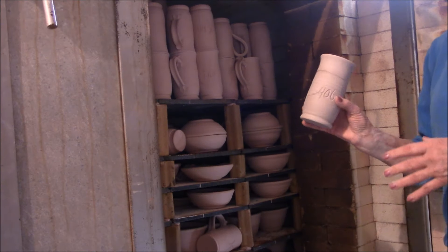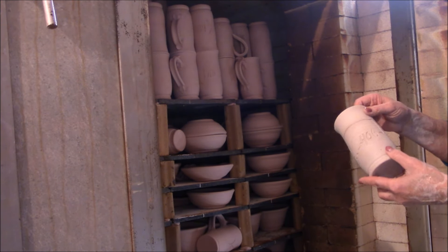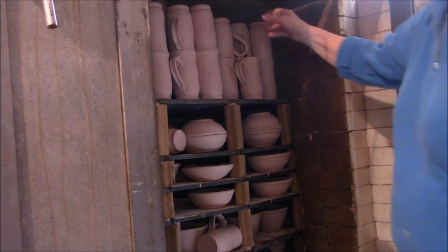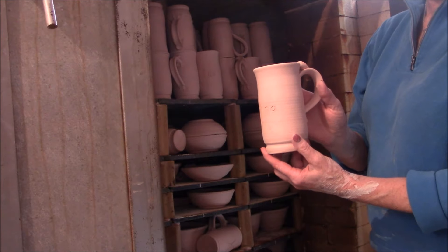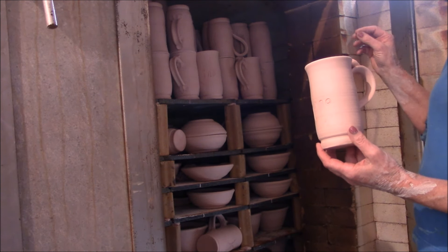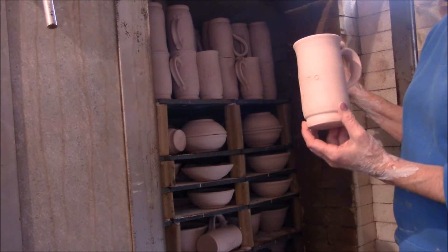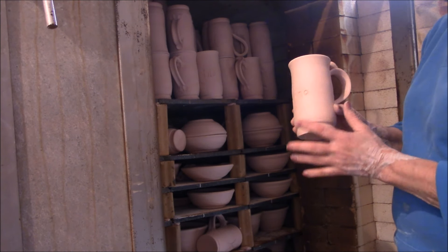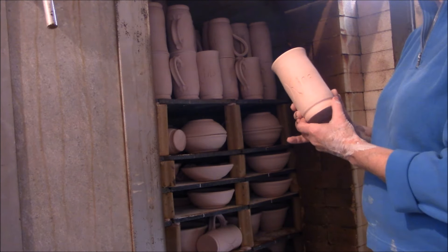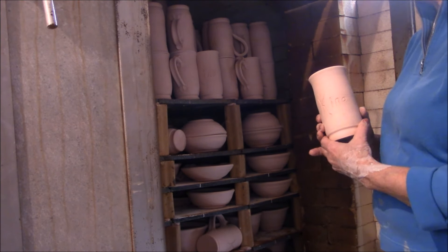On the third day I can unload the kiln. This is a bone-dry mug ready to be loaded into the bisque kiln, fired for three and a half hours. The kiln is plumb full. In the bisque firing, pottery can touch each other — I can put small pieces into the larger pieces to really get a load out. But for the glaze firing, pieces cannot touch. They can be very close — paper-thin close — but if they touch they melt together. The high fire is the glaze firing, and the temperatures are also different.